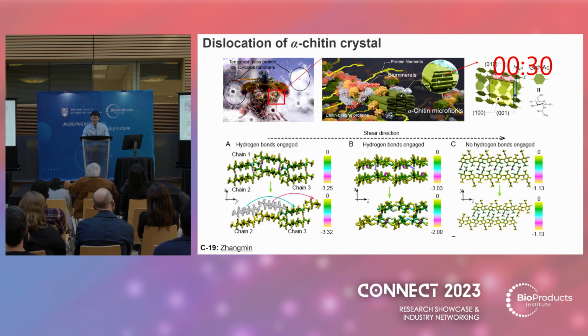So we hypothesize that shear deformation is the dominant source determining the tensile limit of the chitin-based materials. Also, we analyzed the non-covalent interaction between the chitin layers, and we found London dispersion interaction plays the dominant role in determining the cohesion of the chitin-based materials. Also, the adaptability of the London dispersion is stronger than the hydrogen bond, which ensures the recoverability to withstand the continuous shear in the complicated environment of the chitin-based materials.